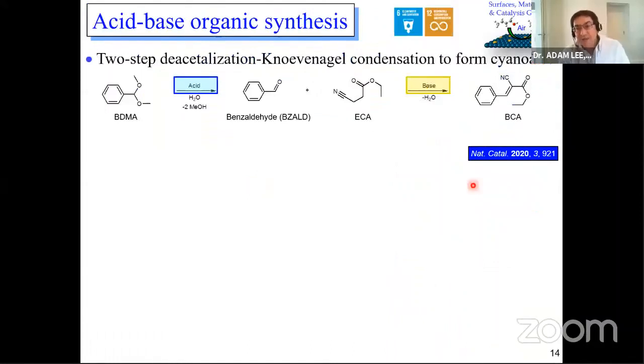So do they work for acid-base cascades? The answer is yes. We recently published this work. Here's an example of a fine chemical synthesis. So here we're looking at highly functionalized molecules in which we have, first of all, an acetal that we're going to do an acid-catalyzed deacetalization. We're going to break these bonds off and convert our BDMA into benzaldehyde. And then we're going to couple the benzaldehyde with an ethyl cyanoacetate to make a cyanoacrylate ester. So these are quite high value chemical products here. So step 1 is acid catalyzed, step 2 is base catalyzed.